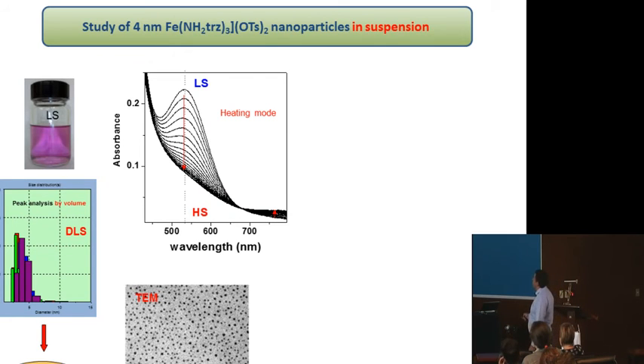These stable nanoparticles were studied by microscopy, but also by dynamic light scattering, and we can obtain a mean value of 4 nanometers for the nanoparticles. It's important to have this suspension because you can, at the same time, measure the size and also the spin crossover properties. For example, here you use absorption, a variation of absorbance as a function of temperature. This way we measure the property of the particles in solution.